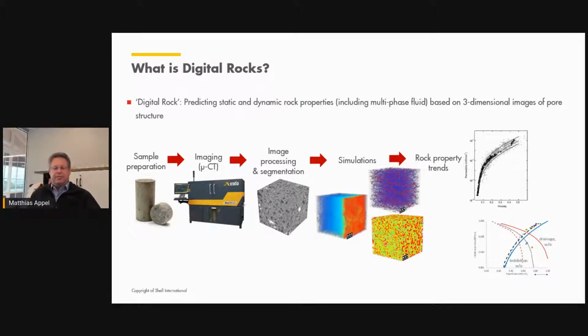And then that 3-dimensional structure is used as baseline for simulating the rock properties. It could be as basic as calculating the void space and deriving porosity. It typically also involves making simulations of a pressure wave across the sample to derive permeability, but also electrical and acoustic properties are typically simulated. Keep in mind, the more complex the simulations are, the more assumptions need to be made for these calculations. A porosity calculation is relatively robust within the resolution of the image. And simulation of electrical properties needs to have a handful of assumptions to cover what basically cannot be seen with the micro CT.